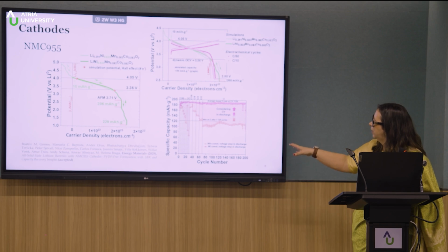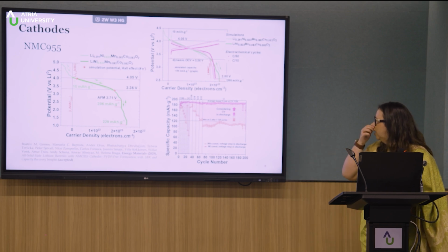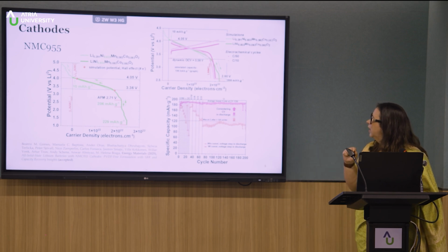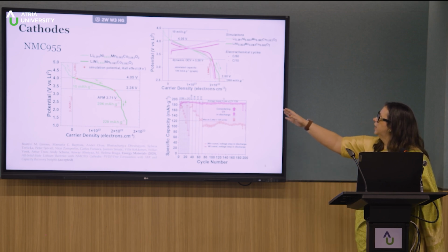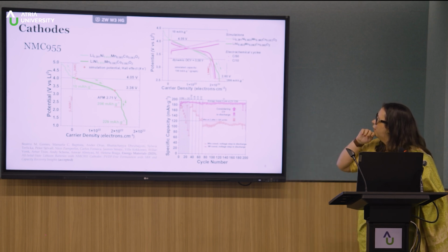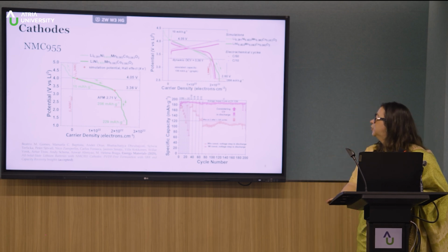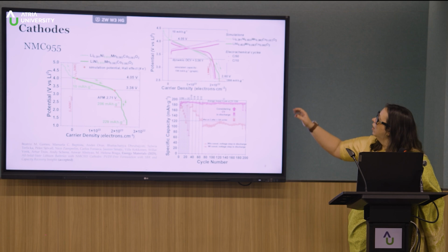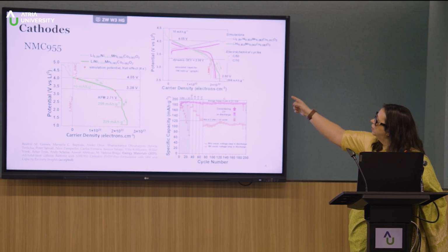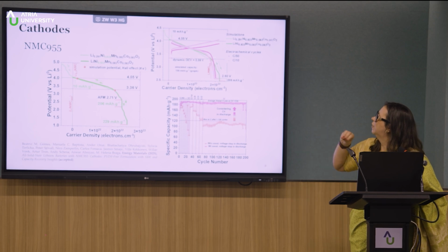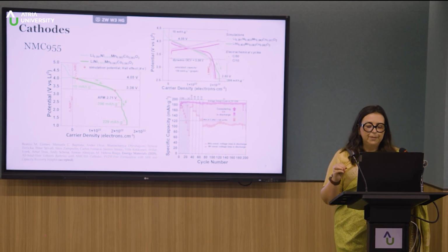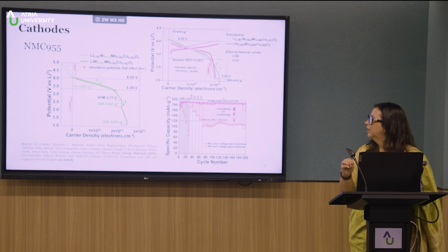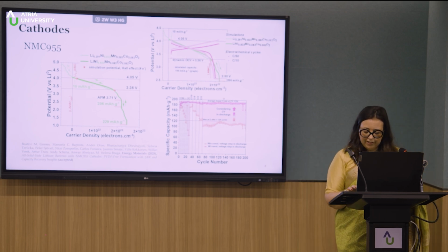So we were able, as I was telling, to charge at 200 cycles, and we were able to discharge at 3C for some cycles, and still charge at C rate for more than 120 cycles with solid state. How? Also because we knew that at the end of our charge and discharge, we had to go to the theoretical capacity at constant voltage. That was very important to keep the integrity of our cathode because of the cobalt. So this is important.